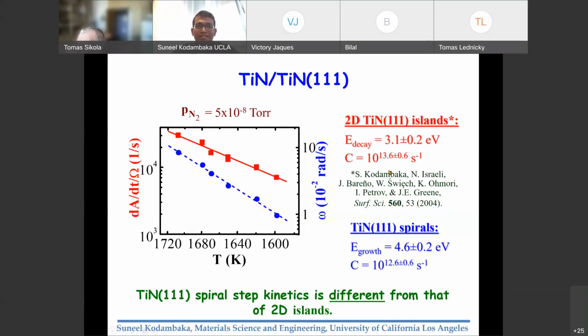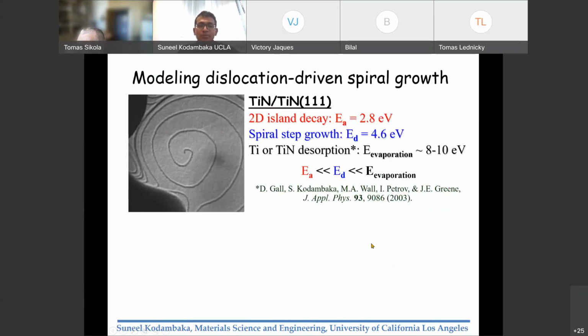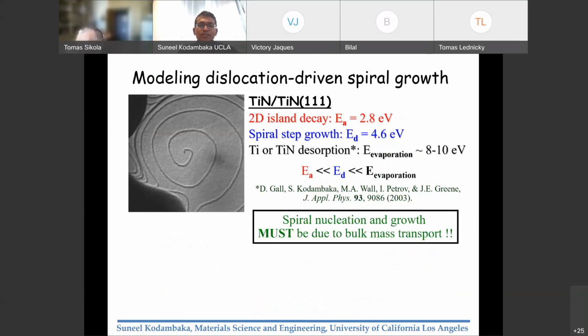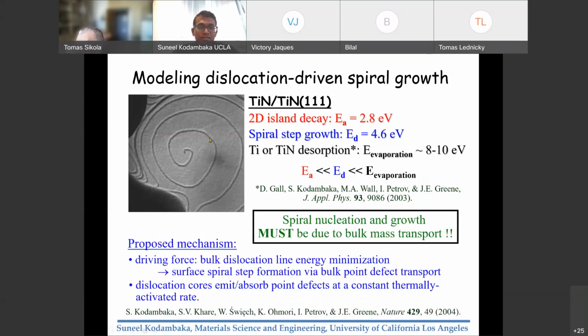So basically what it tells us is that the decay of islands is a phenomenon that's different from the processes that are controlling the growth of the spirals. And so we then came up with the proposition that the spirals must be nucleating and growing because of the transport of atoms from or to the bulk.